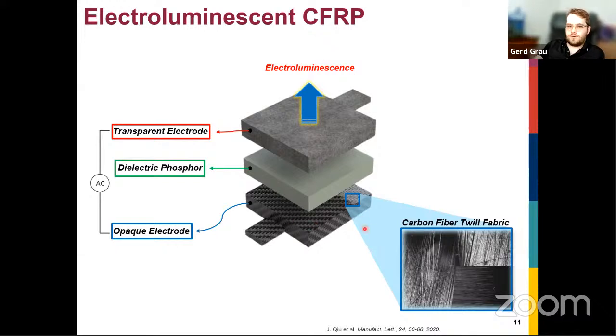So the bottom electrode, which is opaque, is a carbon fiber twill. So this is your actual structural carbon fiber. That's one of the electrodes, which means you don't need to fabricate this electrode with another material. So you save cost, weight, and so on. But also we can then use this to monitor the state of this structural carbon fiber to see, for example, if there's a crack in it or any other damage or strain.